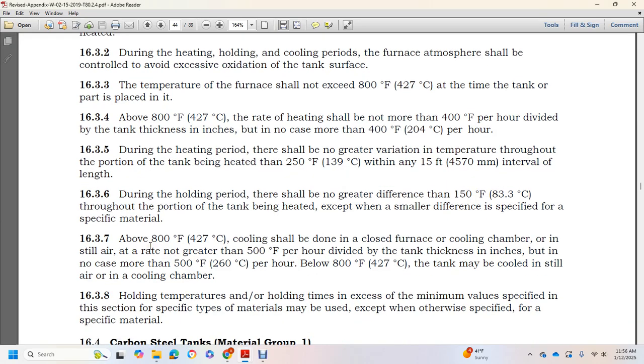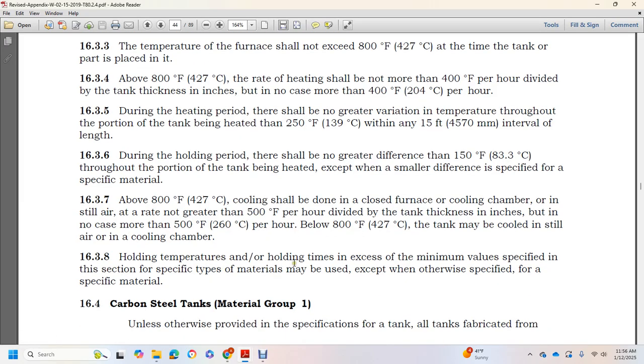Above 800 degrees Fahrenheit, cooling should be done in a closed furnace or cooling chamber, or in still air, at a rate no greater than 500 degrees Fahrenheit per hour divided by the tank thickness in inches, but in no case more than 500 degrees Fahrenheit per hour. Below 800 degrees Fahrenheit, the tank may be cooled in still air. Holding temperatures and holding times in excess of the minimum values specified in this section for specific types of materials may be used, except as otherwise specified for the specific material.